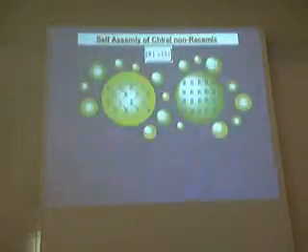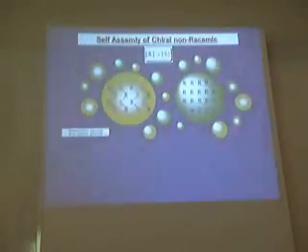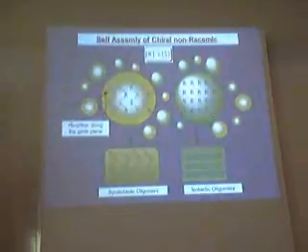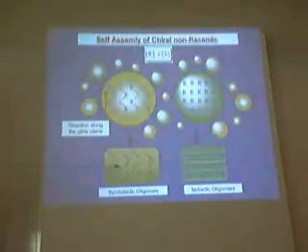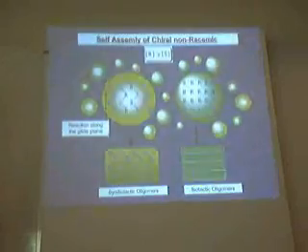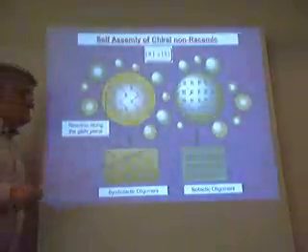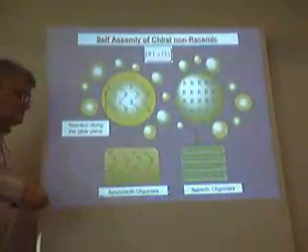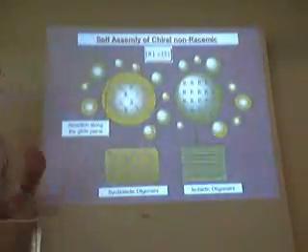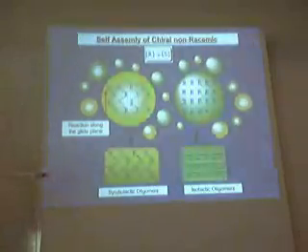Now, this is done on the air-water interface. If the reaction in the racemic crystal goes along the glide plane, you're going to get a syndiotactic oligomer. But the excess which is present here will separate in another phase which is homochiral, and within this homochiral cluster, you can obtain homochiral peptides.